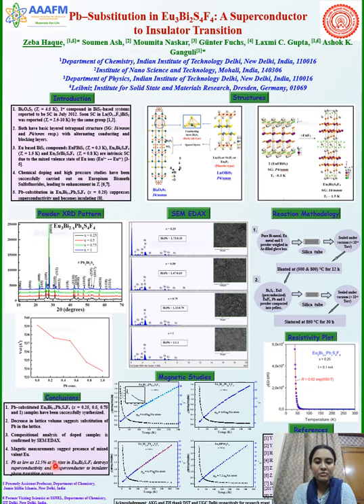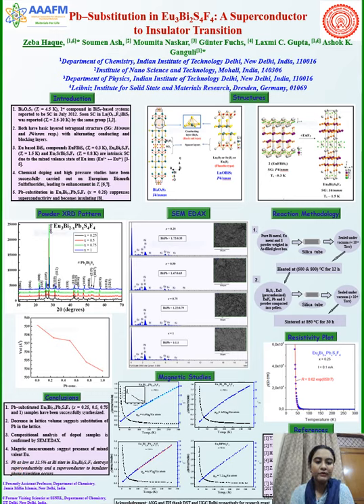The magnetic measurements suggest the presence of mixed valence of europium, and lead doping as small as 12.5 percent at bismuth sites could suppress superconductivity. A superconductor to insulator transition has been observed. Thank you.